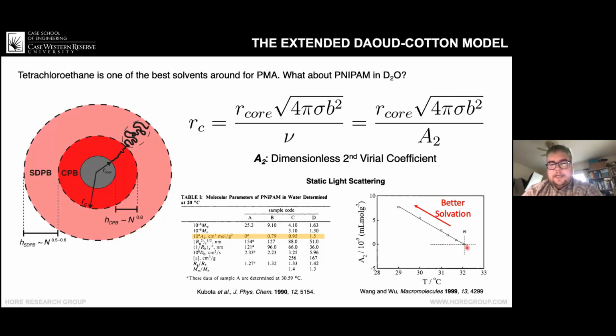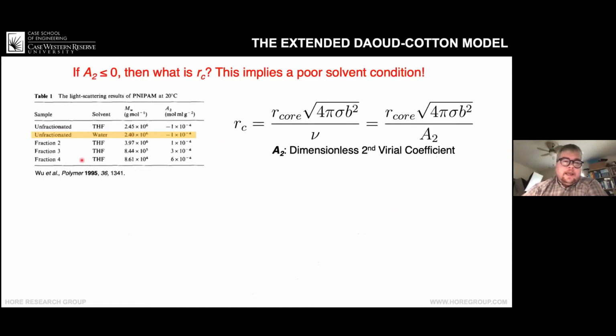But we do see that as we cool down poly-NIPAM, the second virial coefficient is increasing, which shows us that the solvation is getting stronger as we go to lower temperatures. So this has the effect that we're hoping to test. But we can look further in the literature. And this is from 1995. And unfortunately, there aren't that many measurements outside of these three that I'm showing you.